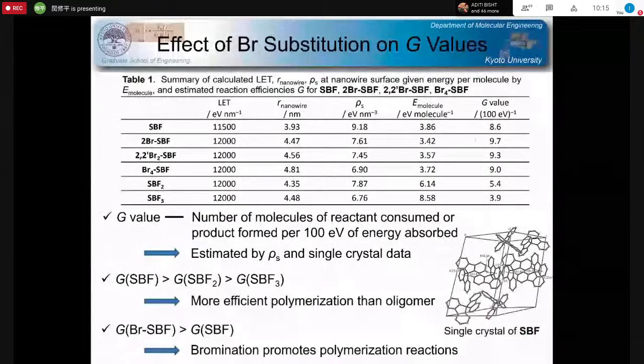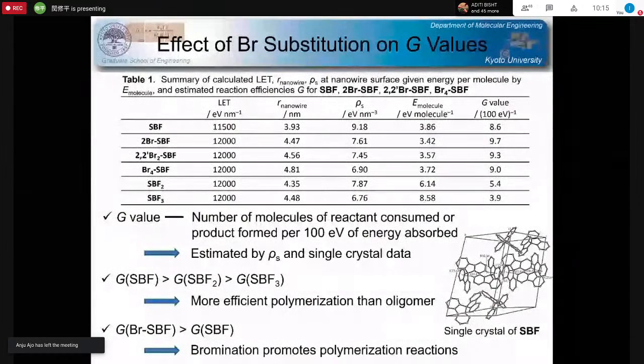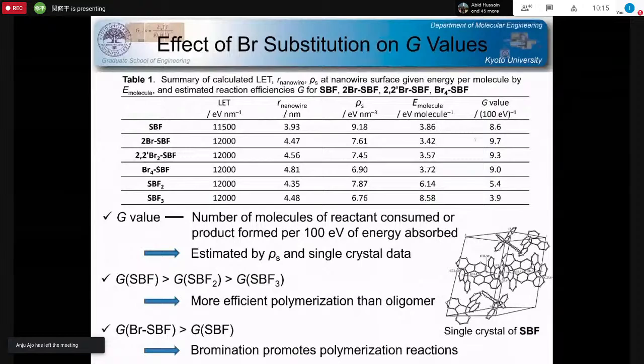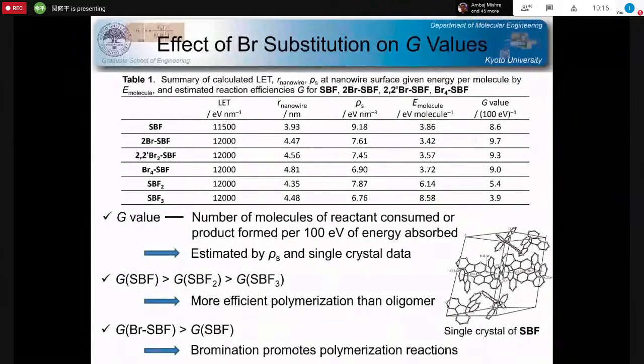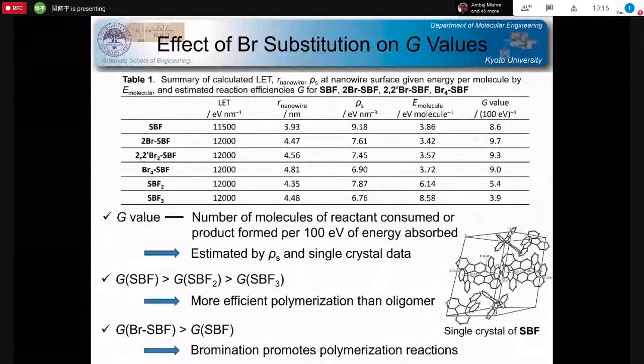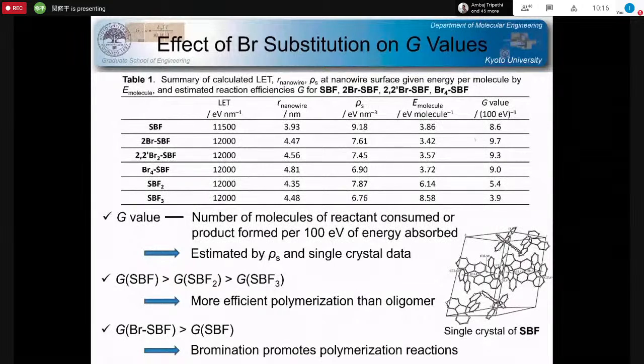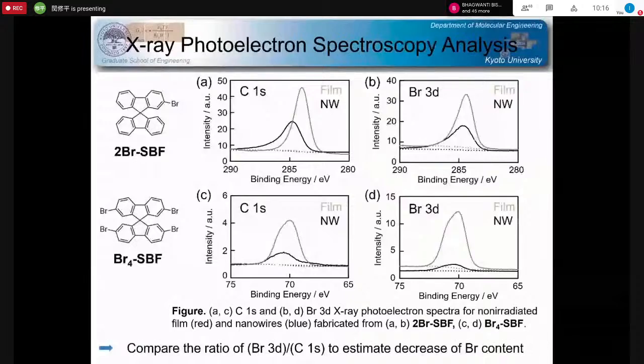And as in the table, the G value, this is one of the most important parameters to quantify the chemical reaction efficiency, was in the range of 8 to 10. And this value suggests that actually the chain reaction was promoted by the single particle intramolecular reactions. Okay.